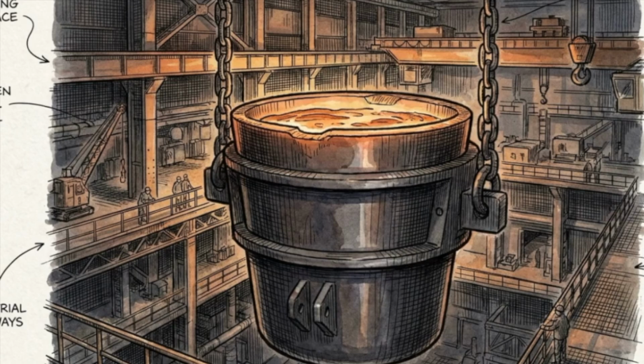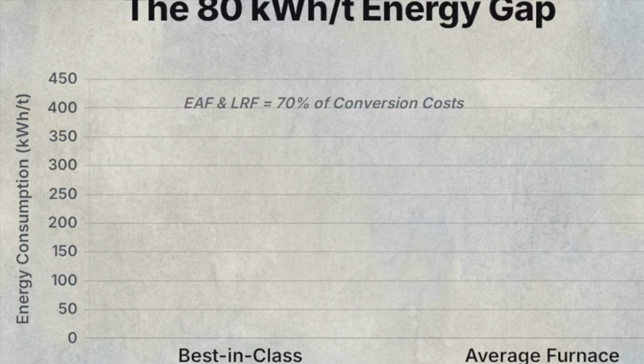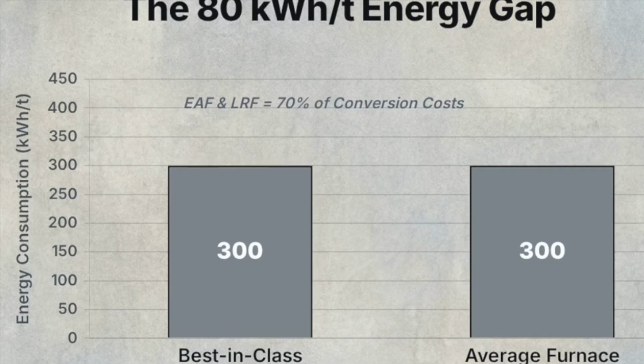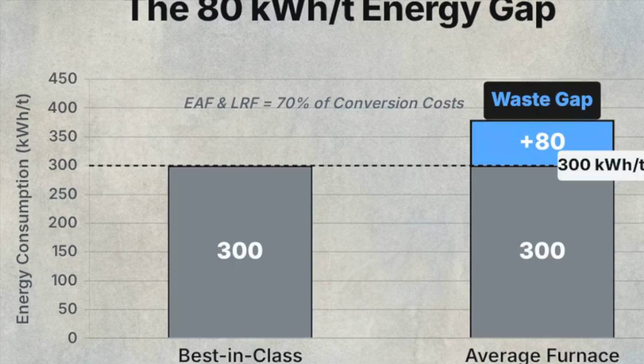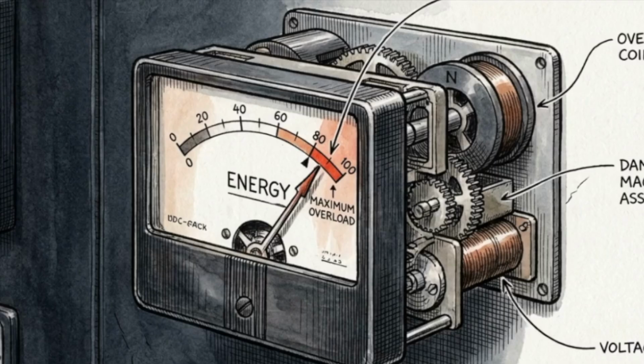Between the initial melt in the arc furnace and the subsequent chemistry adjustments in the ladle refining furnace, you are looking at 70% of a steel mill's total conversion costs. This chart shows the energy gap in those operations. The best-in-class furnaces consume 300 kilowatt-hours per ton of steel, but the average furnace consumes closer to 380. Across an annual production of 500,000 tons, that 80 kilowatt-hour difference translates to $2.8 million in wasted electricity.